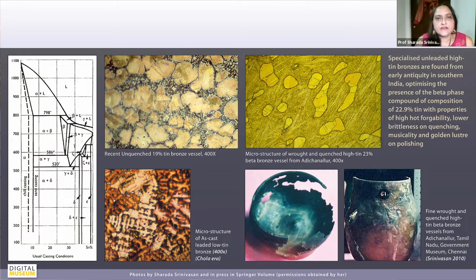And you're looking here at two of the bronze vessels from Adichanallur. And what I found actually was that these are made by a specialized process where unleaded high-tin bronze has been used in early antiquity in southern India, optimizing the presence of a beta phase compound of composition of 22.9% tin, which is an intermetallic compound. And this results in properties of high hot forgeability, lower brittleness on quenching, and musicality and golden luster on polishing.